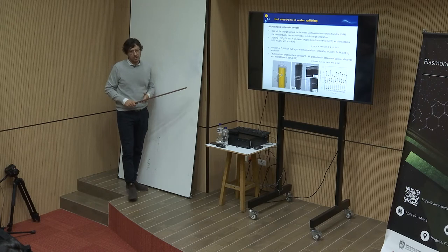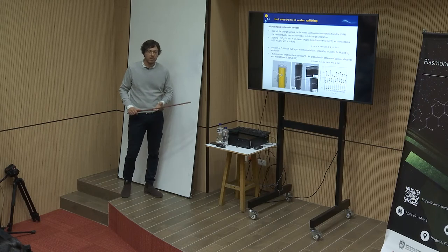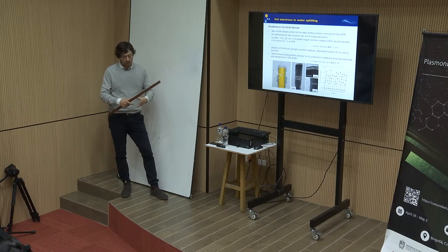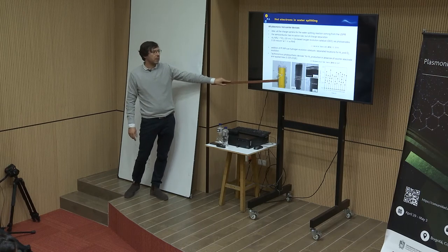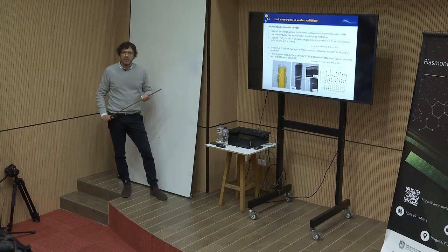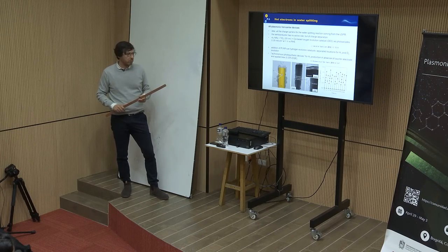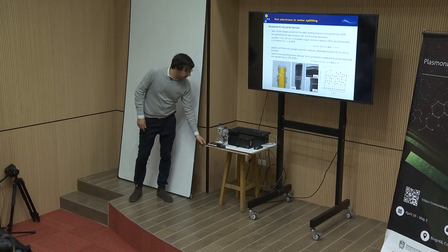And this was interesting because they demonstrated this for photoanodes, for generation of oxygen, for hydrogen production, or just by putting a metal film, where they have this nanostructure, in water, and they saw basically unbiased generation of hydrogen and oxygen. So depending on how you design these structures, if you put the catalyst or not, if you put the platinum or not, they could create different devices which alternatively can be used for hydrogen evolution, oxygen evolution, or both, the overall water splitting, without applying any bias or without providing any energy but the solar light.